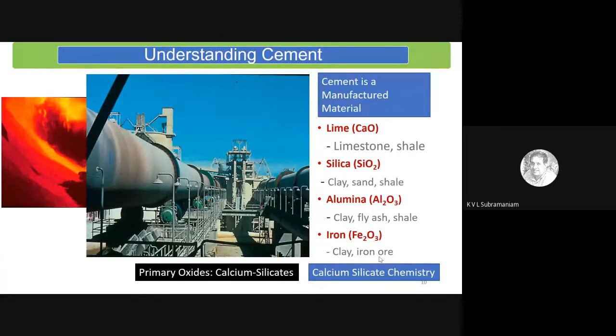Now, of course, clay and limestone are both naturally occurring materials. Clay in particular varies a lot in composition. We know that there are different types of clays depending on the mineralogy, and therefore oftentimes when we use clay in the manufacture of cement, we cannot avoid bringing in alumina, Al2O3, from the clay, and also iron. Clay also contains some iron, and that brings in the Fe component into the cement.